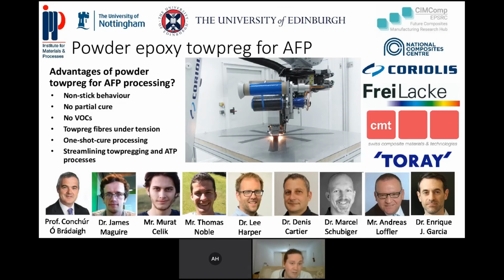and so what are very much the advantages of a powder epoxy system? You don't have any stick behavior. You can see this blue PTFE tape here. Well, you don't need that with our system, as the tape is not tacky at all. There's no partial cure, so you get much better interply properties, as it co-cures 100%. There's no VOC emission, another very good point, as the fibers are kept under a glassy material. The melted powder then comes back and is in a glassy state. We keep the fibers always under tension, so we've got a better alignment.